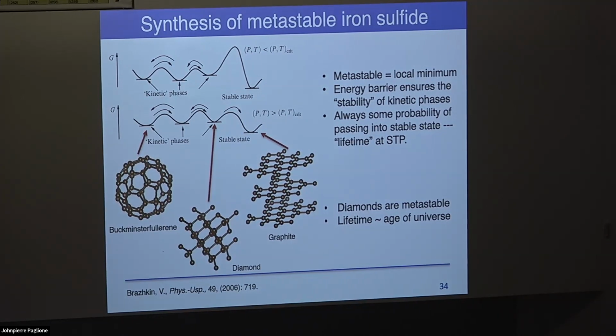But if you're using a traditional solid state method where you go to very high temperatures, you're always going to go over this energy barrier and go into your stable state. That's pretty much always going to be the case. But if you're at maybe the perfectly correct pressure and temperature regime, you might be able to stay stuck in one of these kinetically stable states, one of these metastable states.